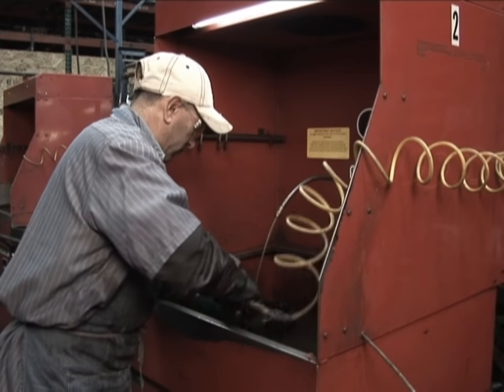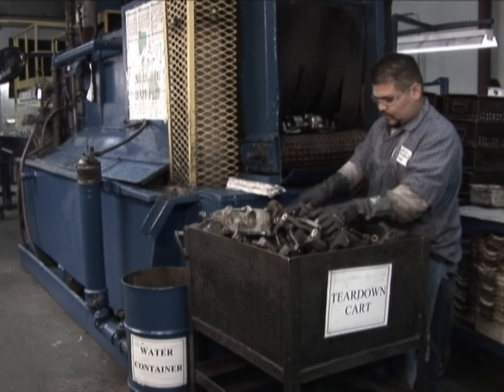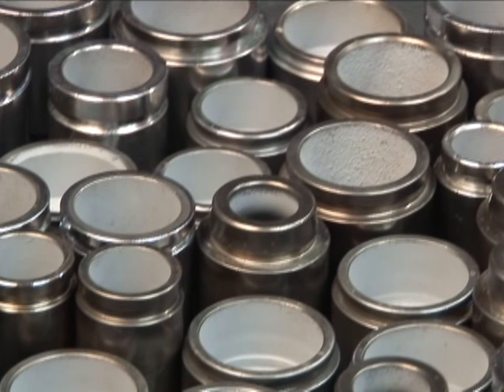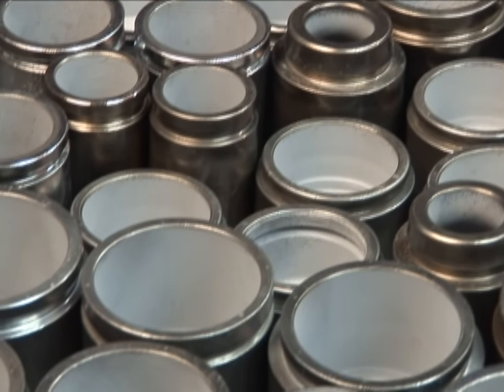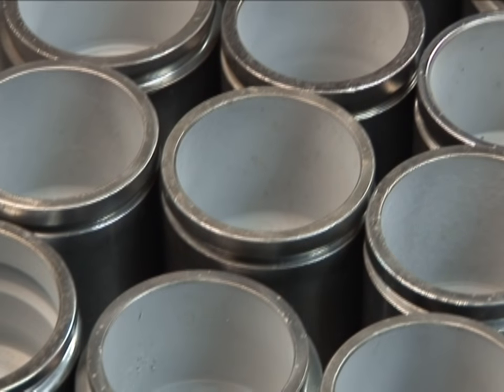The blind pin bores on each bracket are washed, wire brushed, and blown clear to remove old hardened grease. All disassembled caliper components are hot water washed to remove any grease and residual fluids. The interior surfaces of used steel pistons are sandblasted, then rock tumble washed. The insides of salvaged pistons are sprayed for rust protection and cosmetic appearance after a rigorous inspection where about 50% of pistons are rejected due to rust, scratches, or dents.